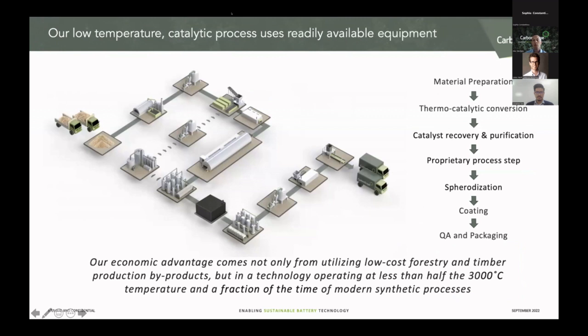In terms of our process, it's a continuous process. So that's very different from the traditional batch processing in other graphites. It's also a lower temperature process, so it's less than half of the 3000 degrees C that a conventional graphite process would need. It also uses a clean catalyst, which we recover, versus some of the other catalysts in other processes, which are less environmentally friendly.